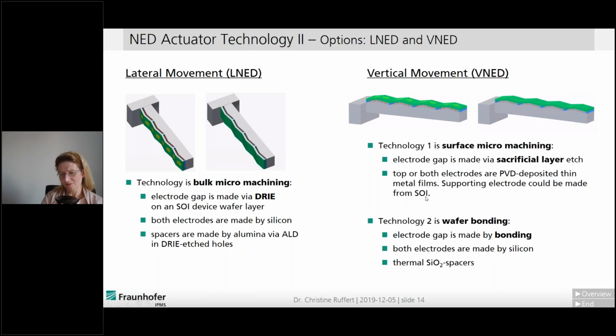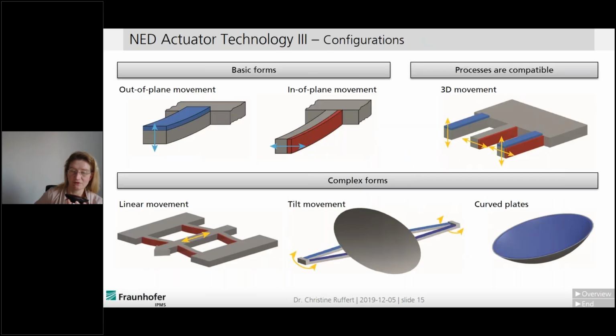Alternatively, we can use wafer bonding. So we take two wafers and create the gap by bonding of these two wafers. In this case, both electrodes are made of silicon and the spacers are made of thermal silica. So these are the main configurations, and we can of course combine them.